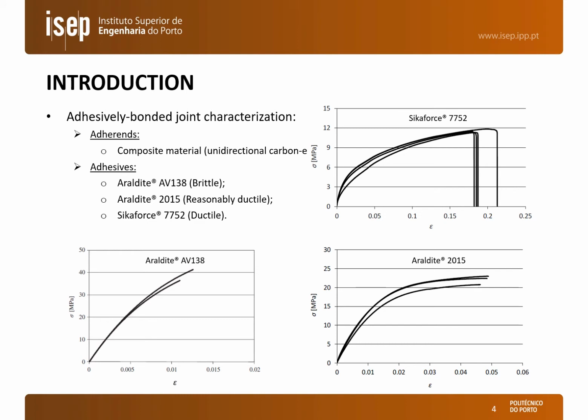To begin with, a short introduction on the adhesively bonded joint characterization. The adherends were made of a composite material, in this case a unidirectional carbon epoxy prepreg, and three different adhesives. The Araldite AV138 is a brittle adhesive. The 2015 already has some ductility, around 5%, as we can see in the figure to the right and below. And finally the Sikaforce 7752 is the most ductile of the three adhesives that we are testing here.